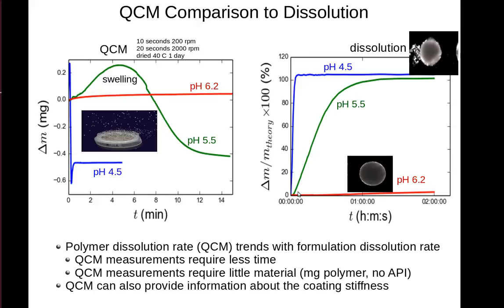However, the QCM measurement is seen to be done in approximately tens of minutes, whereas it takes several hours to do a traditional dissolution, and that's because of the amount of mass. The QCM measurement uses approximately a few tenths of a milligram of polymer. It also requires no API, therefore avoiding the complication of having to prepare microspheres.